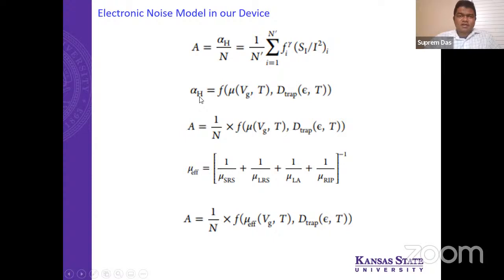Now this alpha should be a function of mobility and traps, because how much noise there is depends on how mobile the charge is, but also on what is the rate of generation of these traps in the interface. So we do not know the exact form, but we know that it should be a function of mobility and the trap states. And again, it's a very complex function, because your mobility depends on the electric field and the temperature, and trap state depends on the depth of the trap states from the oxide or interface, and the temperature. So it's a very complex function. But if we use it like this, then we can write your noise amplitude as 1 over N times this function, which is basically your alpha.